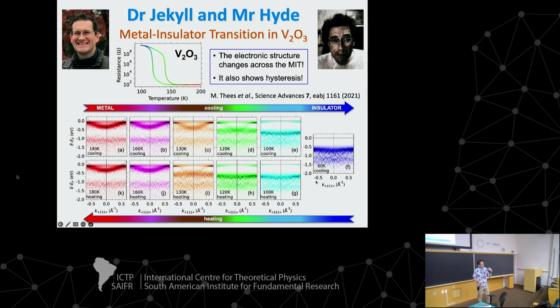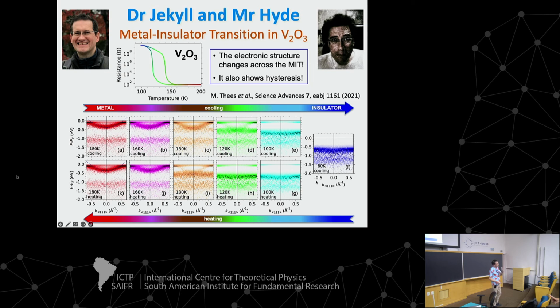So what we need to do in order to analyze the spectral function is come back to the raw data, but then it will be more complicated because the background in these systems, in most of the oxides, is really large. So you need to subtract the background, you need to start doing a more complicated analysis, and then you need to check whether your analysis remains true when you change the different assumptions that you have made to fit the background and to fit other things. But so far, I don't have an answer to your question.